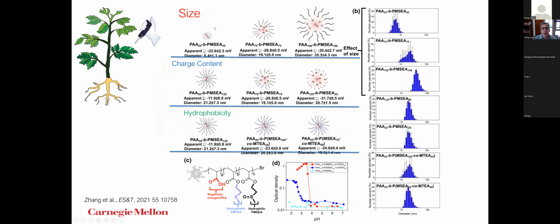All right, so what have we done here? Elin made a whole series of polymers with different cores and different shells. We looked at something like size. So we have small, medium, and large, and you can see these top three are the sizes. They're fairly monodispersed, and there's limited overlap between the sizes. All their zeta potentials are pretty similar to each other. So we can look at size. Another set was exactly the same size, but they had different charge contents associated with them. And you did that by changing the core to shell composition, and the core has charge and the shell does not. So the more core you have, the more charge content you have.